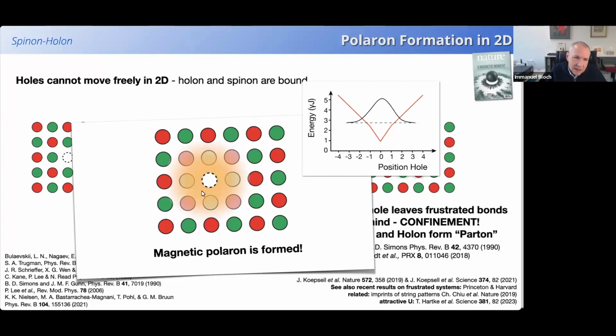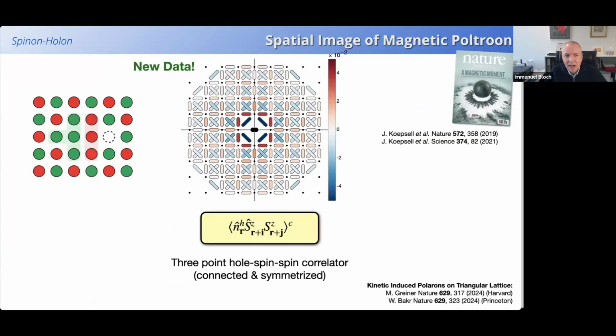You can think of them as an original hole, a dopant, surrounded by a cloud of modified spins, of spin distortions in the system. Whenever this hole moves, it has to drag around with it this entire cloud of spin correlations. So that's basically our meson that is formed in this system. And here's actually a picture of such a polaron, this dopant surrounded by this modified spin correlation. Let me walk you through this graph because it's quite complicated. It's a beautiful example of a highly non-trivial spin correlation function that you cannot measure in a real condensed matter system.